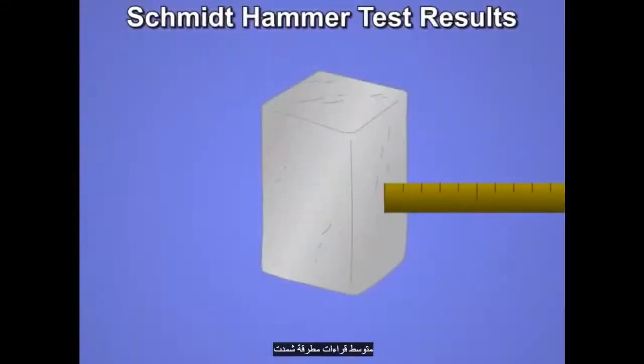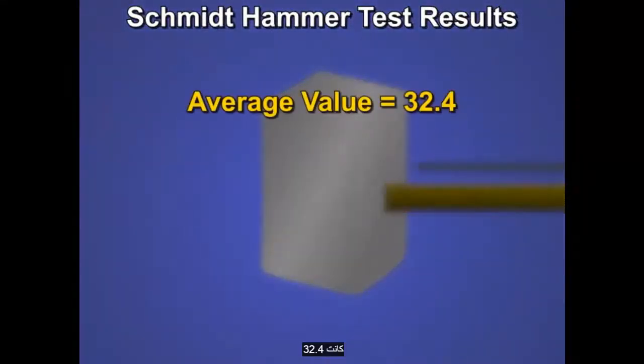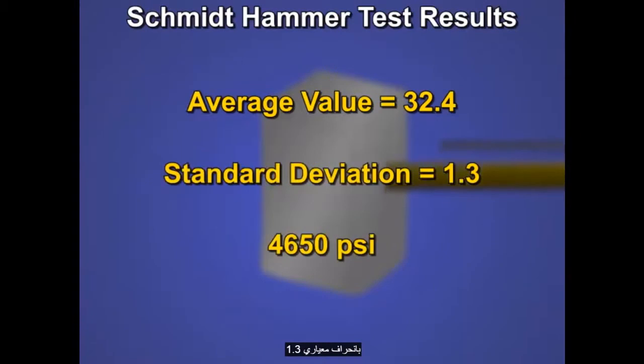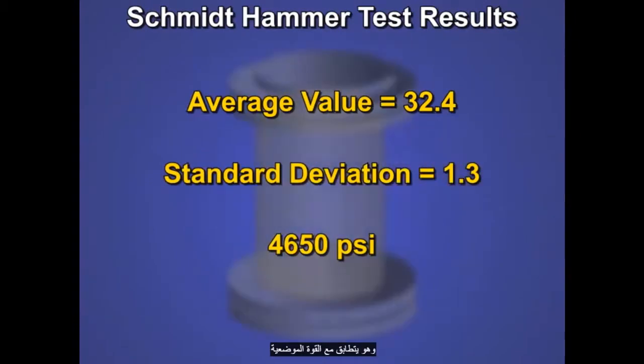The average of the Schmidt hammer readings was 32.4 with a standard deviation of 1.3, which correlates to an in situ strength of 4,650 psi based on calibration to parallel laboratory cylinder tests.